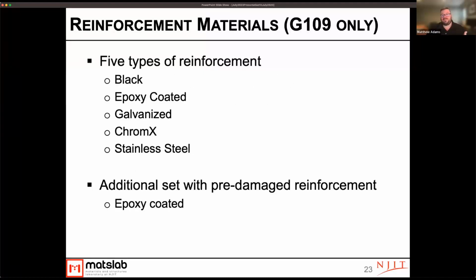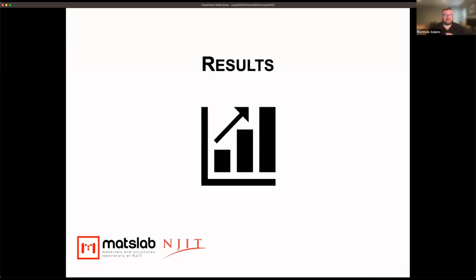We also looked at 5 different types of reinforcement materials in the G109 test. And then we also took a set of epoxy-coated reinforcement, and we pre-damaged them basically by breaking off a little bit of the epoxy coating to simulate the performance of those materials in the field, where epoxy coating, while it works great when that epoxy stays on, is a little bit more prone to damage, and that can really impact the performance of it. So here are our results from this study.